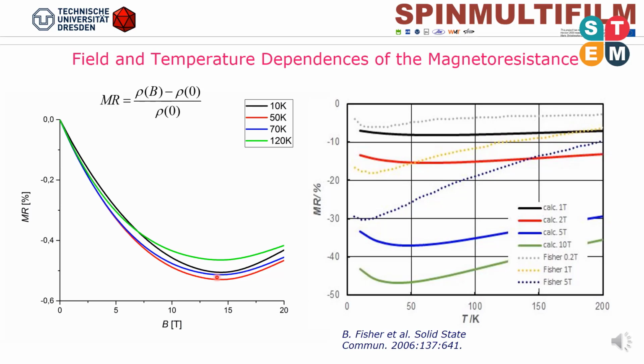The location of the minimum of the model depends on the value of the parameter gamma. With increased gamma, it shifts to lower fields. The predicted temperature dependence of the magnetoresistance in nano-size granular strontium ferromolybdate, strontium molybdate core shell structures is much weaker than in strontium ferromolybdate ceramics. The weak temperature dependence is a consequence of the parameter T sub 0 in the order of the temperature at resistivity measurements.